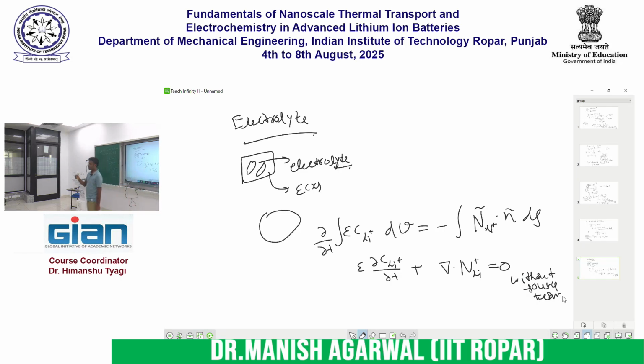But we have the source term, right? Because there is a flux of the Li plus that is there. Earlier when we were modeling the micro scale, we wanted to resolve the interface. That's why we didn't take it as a source term. But now we don't want to do that, right? So the source term is going to be again b, which is same as previous. The source term is similar, again J, that we have calculated as J average, and then divided by the Faraday constant, because again we want the number of moles, not the charge, right? So again the similar kind of thing.